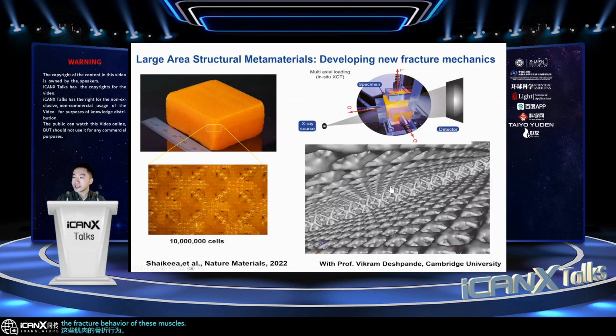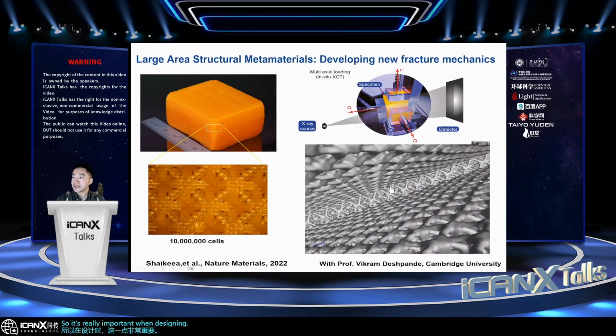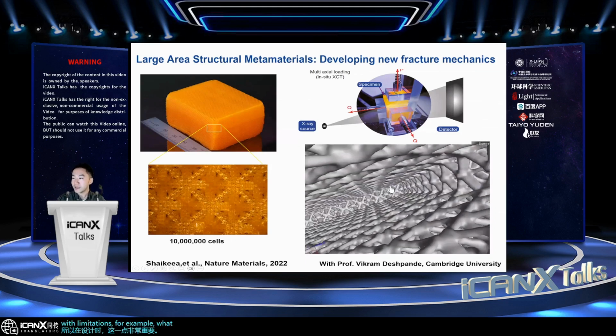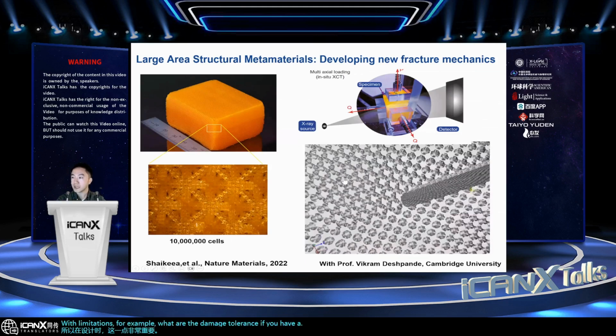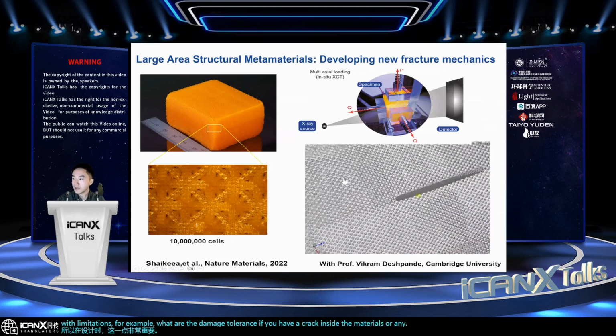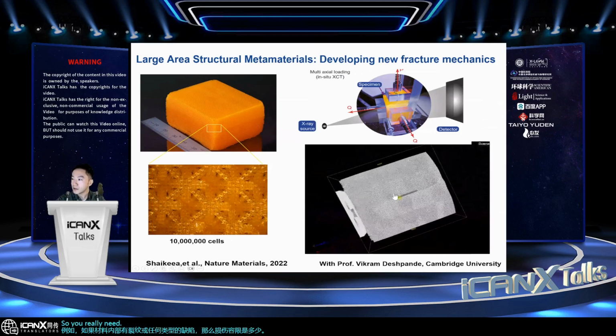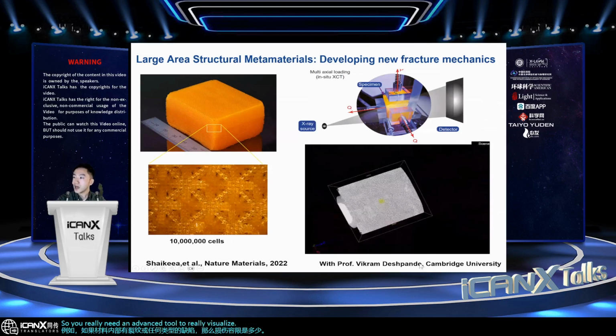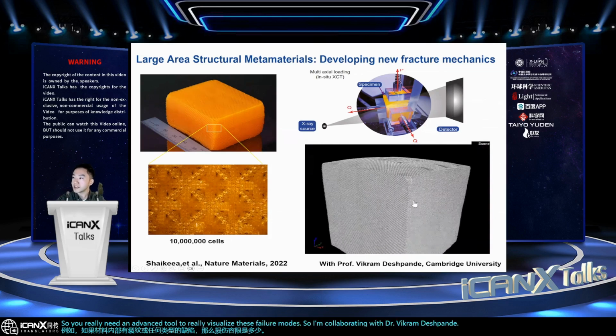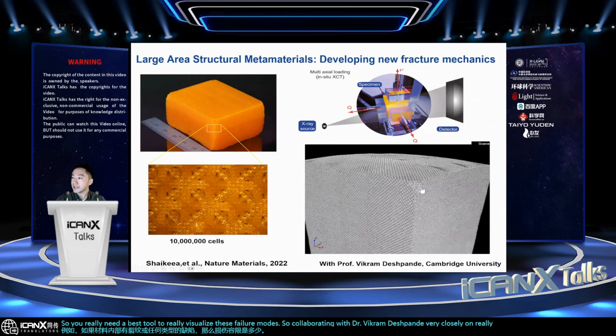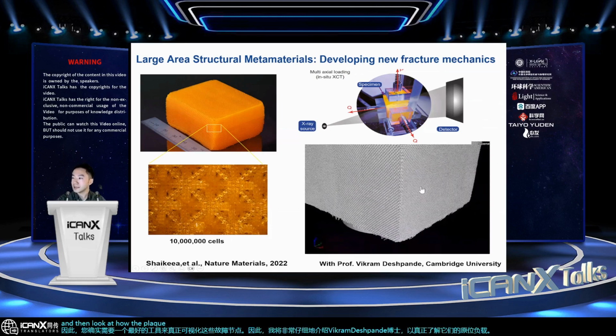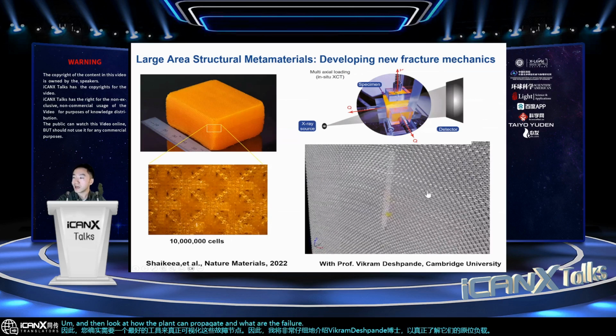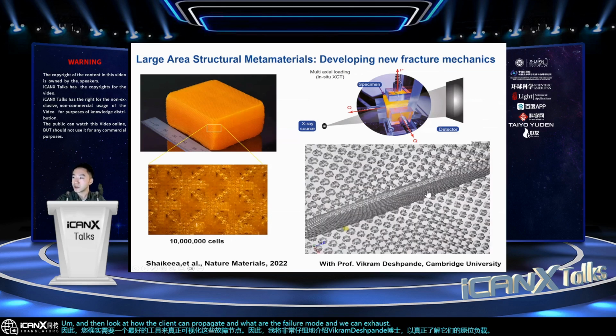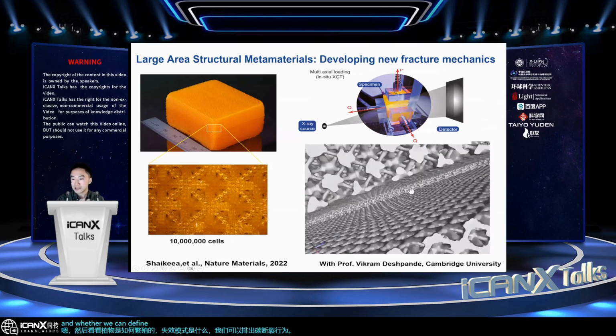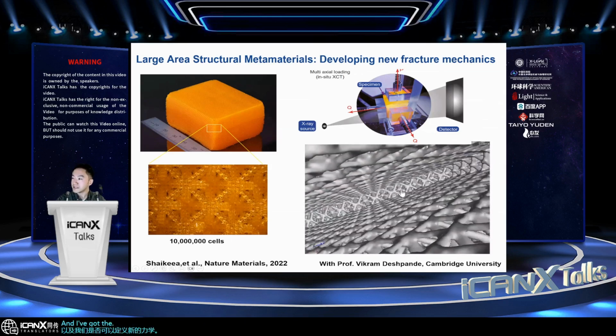It is really important when designing materials with limitations. For example, what is the damage tolerance? If you have a crack inside the material or any type of defect, how does it behave? So you really need an advanced tool to visualize these failure modes. We collaborate with Dr. Vikram Deshpande very closely on looking at in situ loading, and at how the crack can propagate, what the failure modes are, and what mechanics laws govern the fracture behavior of this metamaterial, and whether we can define new mechanics that define the failure behavior of this material.